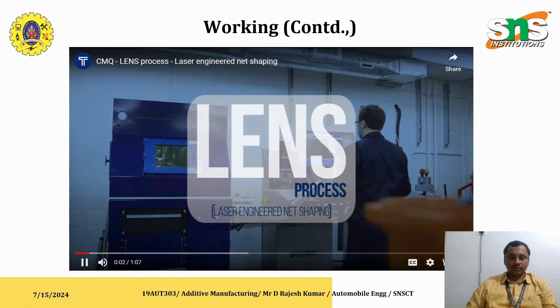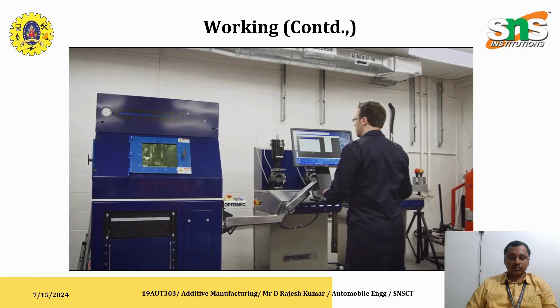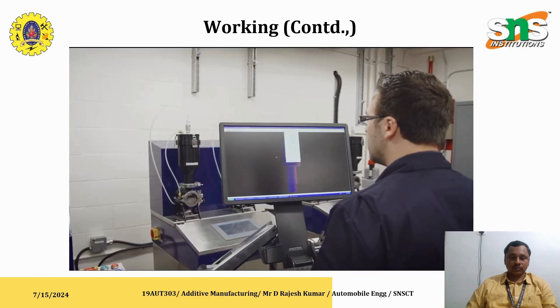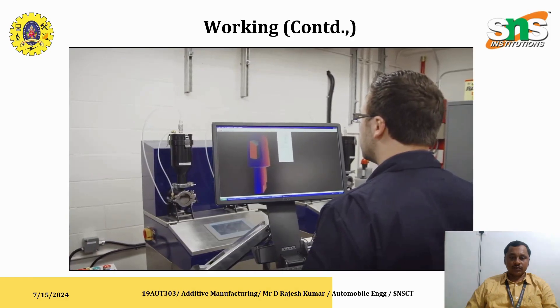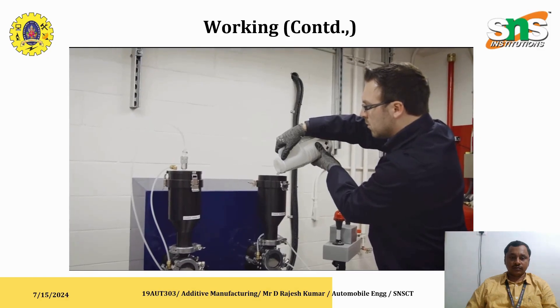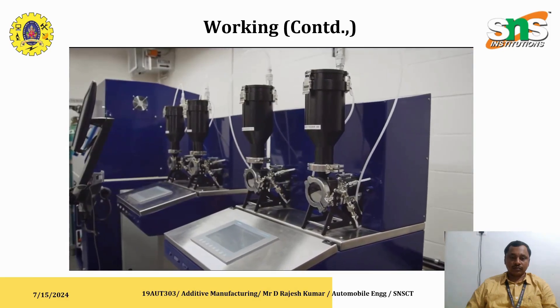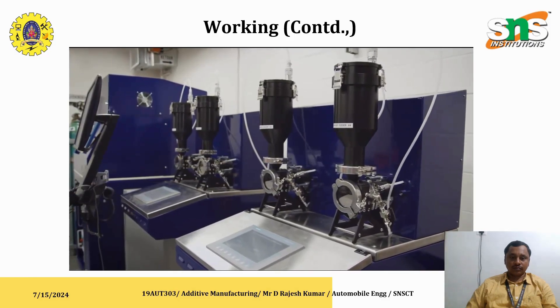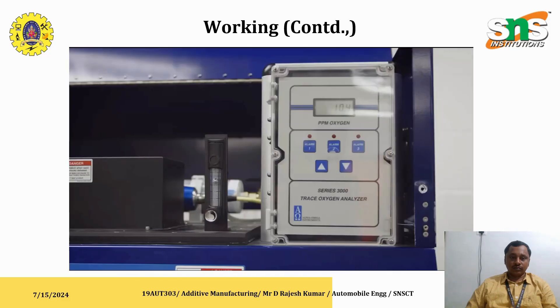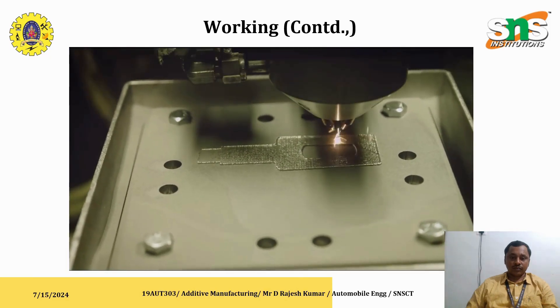Laser Engineered Net Shaping, or LENS, is an additive manufacturing process in the directed energy deposition category. It uses powder sprayed into a laser to produce fully dense parts with a high deposition rate. A 3D drawing is imported into the device software, which divides the part into multiple layers. The powder is placed in a dispenser ensuring constant flow; more than one type of powder can be used, allowing production of parts with chemical composition gradients. The chamber is flushed with argon to obtain an atmosphere containing a few ppm of oxygen.